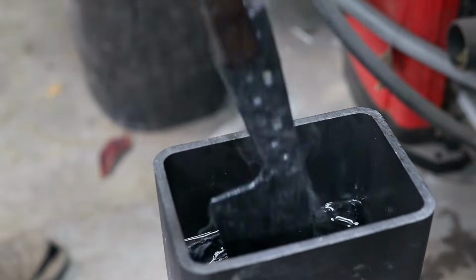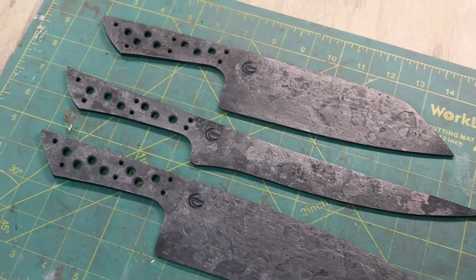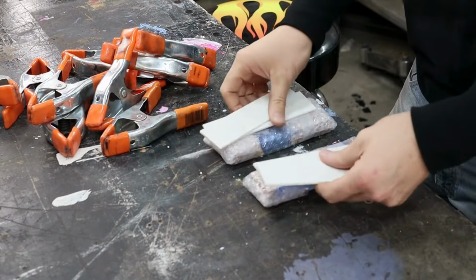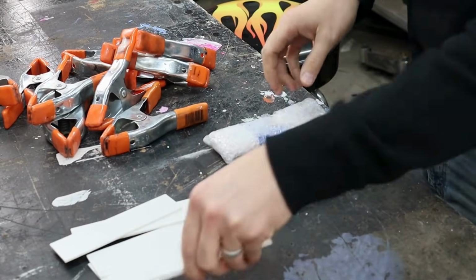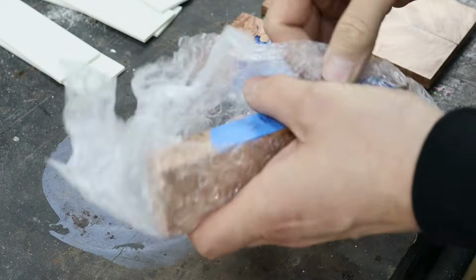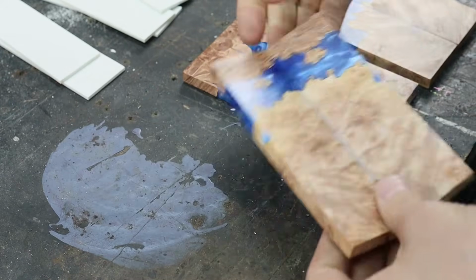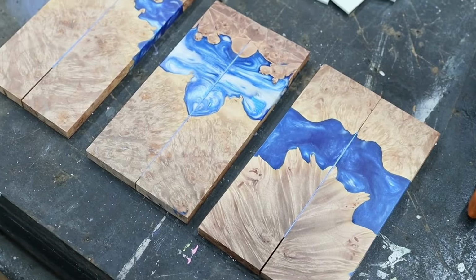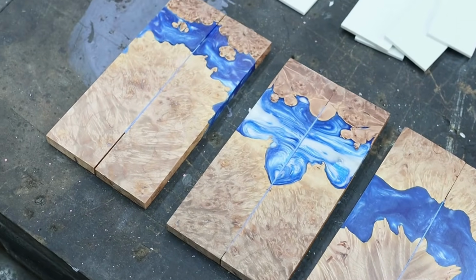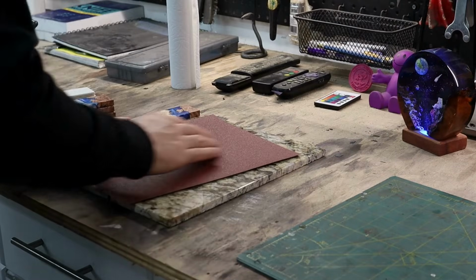One of the nice things about having a larger volume quench tank is that the overall temperature doesn't change a ton with each knife that you quench. You see much more dramatic changes in temperature with tanks that hold less than a gallon of quench oil. This one holds about 3 gallons. I tempered the 2 chef knives at 400 degrees Fahrenheit and the fillet knife at 425 degrees Fahrenheit.